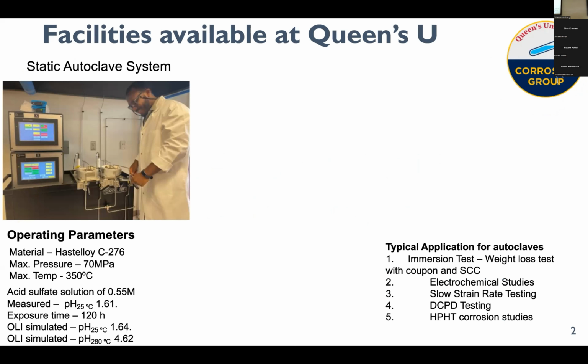In our lab, we have a static autoclave, which I use for different experiments. It is made of Hastelloy C276, and can go up to a maximum pressure of 70 megapascal and a maximum temperature of 350. So currently I'm doing